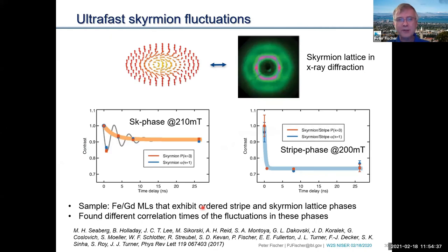And what we found, and I think this is a pretty remarkable finding, and this is shown here in these two graphs, is that when the system is in the skyrmion phase at 210 millitesla, a certain field, the characteristic fluctuation time scales are drastically different than if it was in the stripe phase. So by just slightly changing the field, by slightly rearranging the spin configuration in the skyrmion system, going from the stripe phase to the skyrmion lattice, the characteristic fluctuation times, correlation times, are vastly different. And this, at least to me, is still a very interesting observation, because why would the system even care about fluctuations, which sound more like just random fluctuations? It looks like there's much more to discover here.